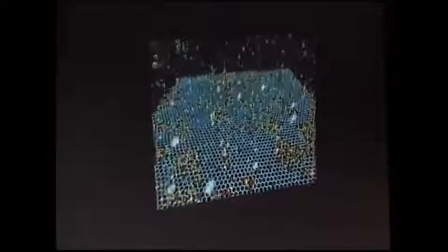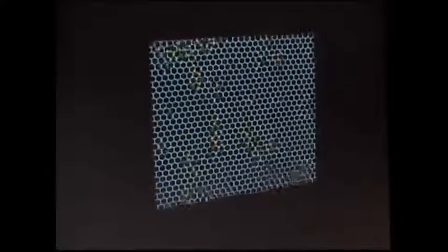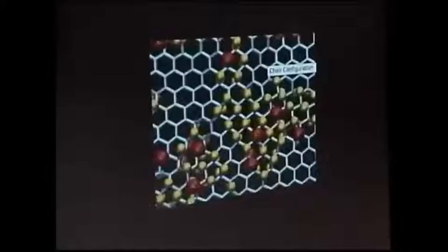Why? Because the fluorine comes here, deforms the lattice, brings some sp3 hybridization in the region, and then it becomes more reactive, and then the hydrogen connects easily. Okay. Then we have several small domains formed, and then we will show one of those structures that I cited here. We have a chair configuration here. Okay.